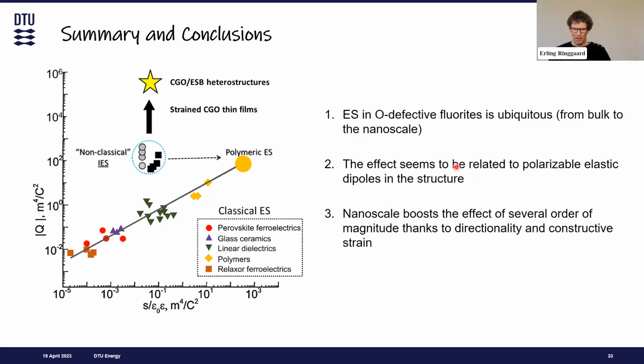Yeah, good. The last question for now is, if we replace a small cation with a big cation in a cluster, what will be the effect on electromechanical properties? That's a very good question, and I have a partial answer for that. We have seen that if you go close to the solubility limit with your cations, so if you strain your system a lot in terms of electrostatic effects of the cation on the vacancy, we basically suppress the low frequency response, but we get a steady response at high frequency.